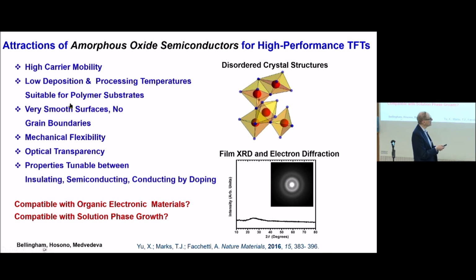Low deposition temperatures, you say, what's the big deal? I want to grow them on plastic. That's the big deal. So I want to go at low temperature. Very smooth, no grain boundaries, mechanically flexible, optically transparent, properties tunable between insulating and semiconducting by doping. So we're always asking something that is tough: are they compatible with organic materials? Could you grow these films from solution?